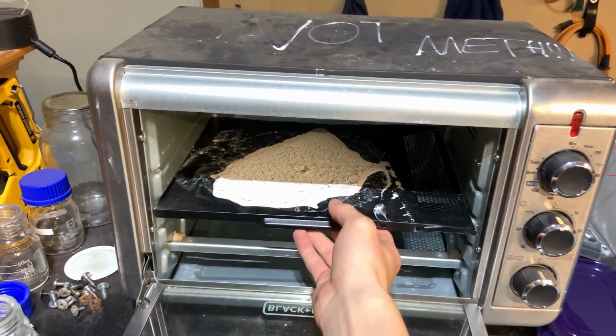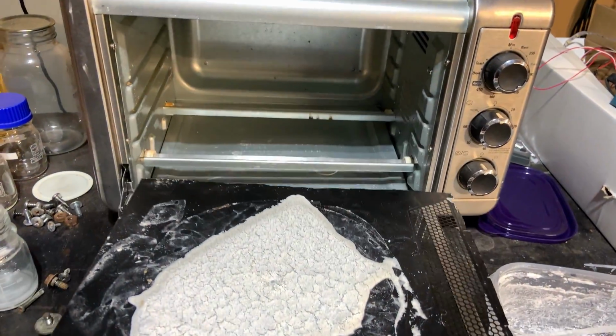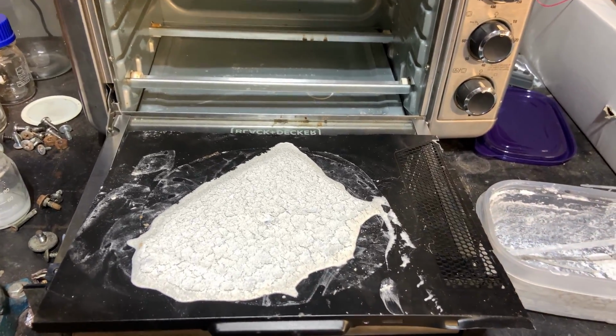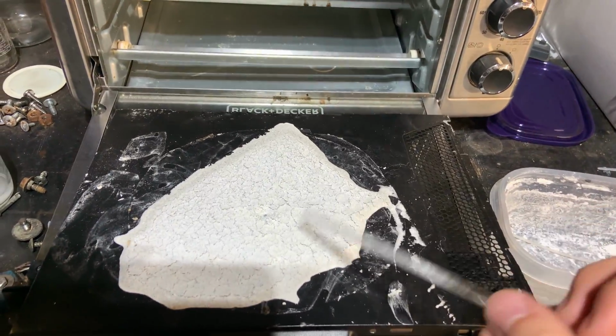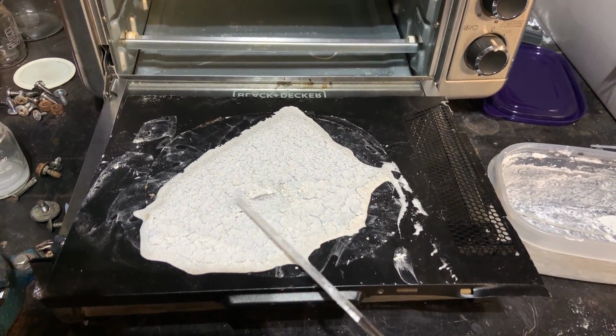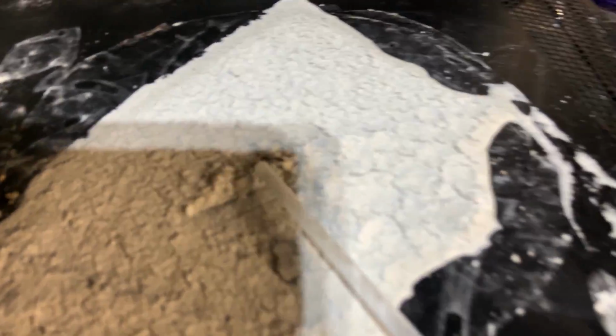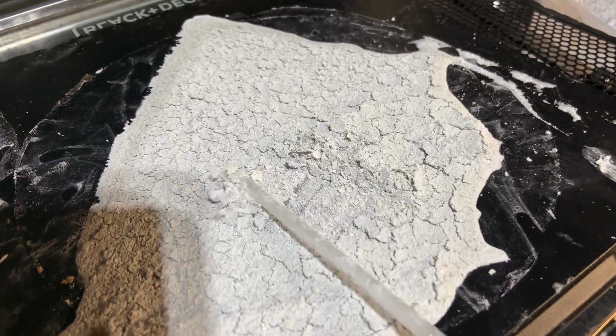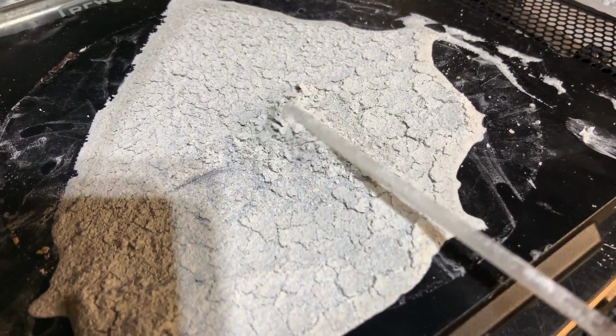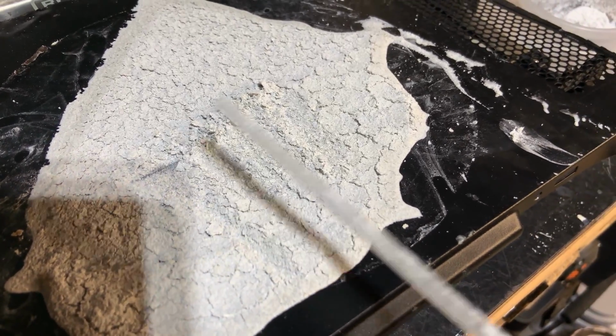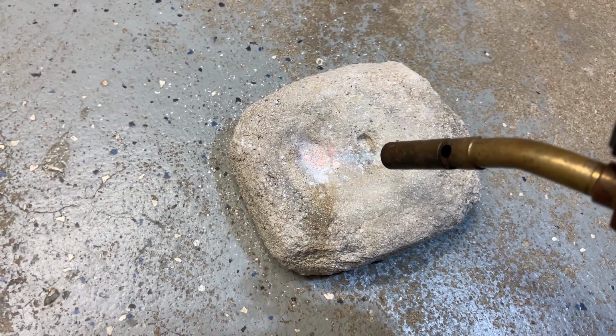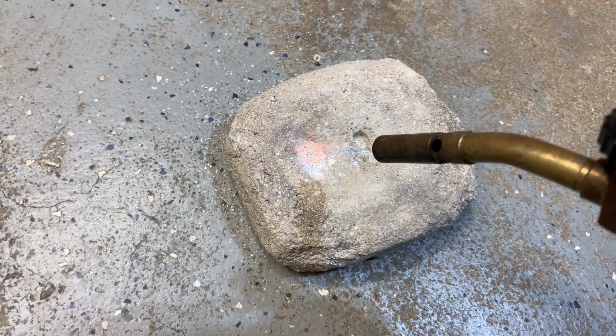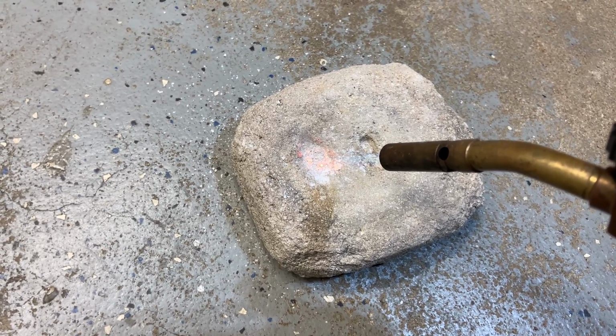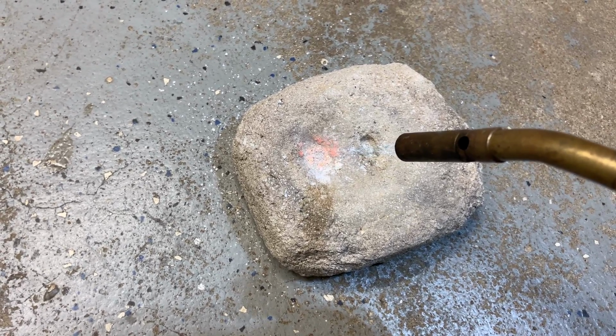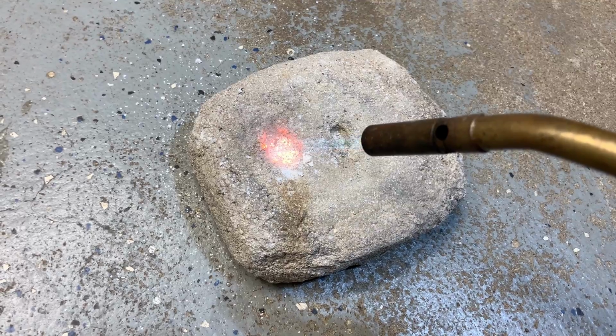There isn't very much of it, the reaction goes really slowly, and I believe there's a lot of impurity of magnesium hydroxide in it because of how much of the Epsom salt electrolyte I actually used. I believe that the Epsom salt actually gets prioritized first before the actual electrode starts degrading, so in a future run I actually dialed it way back. Then I heated it up to try to convert as much of the hydroxides to oxides as possible,